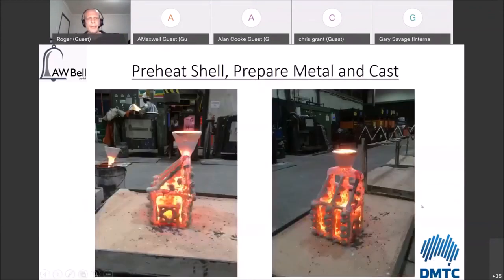So this is so the shell is then preheated. You prepare your metal and cast it. All of this part of it now becomes pretty routine, pretty straightforward. On the left-hand side, you can see it straight after casting, and it's always one of these things with investment castings. We get the ability to take a photo of the part just after it's been cast, so we get to see what its thermal profile looks like while it's cooling down. And that gives you a good idea about whether or not you're on the right path, of course.